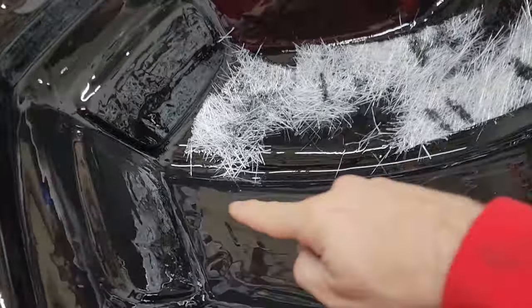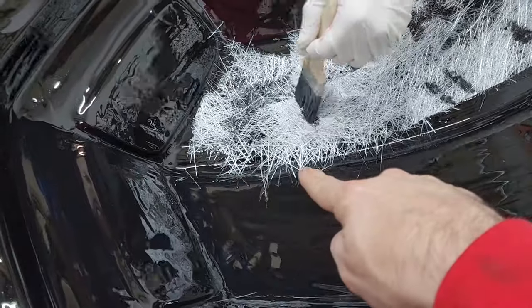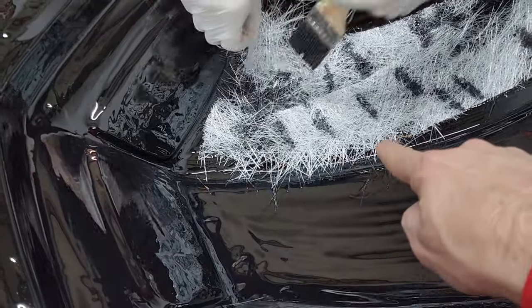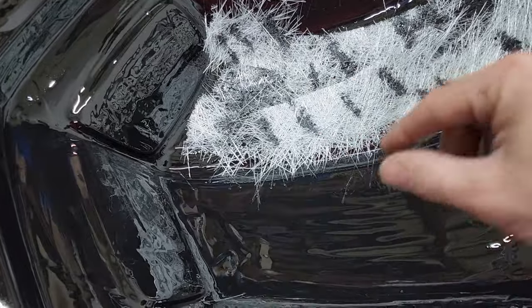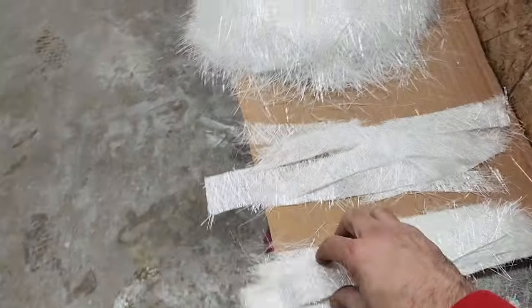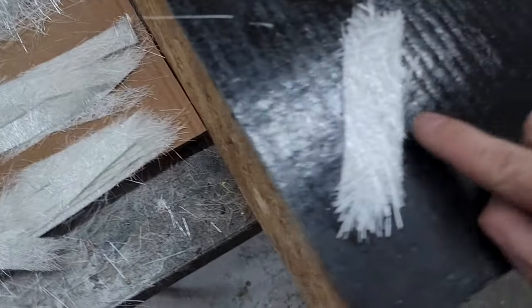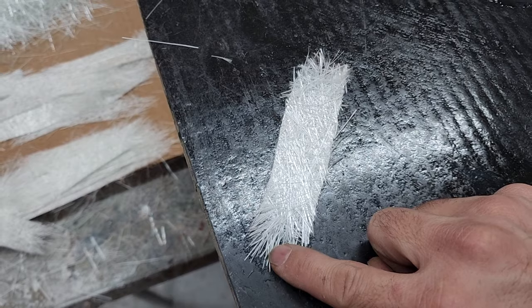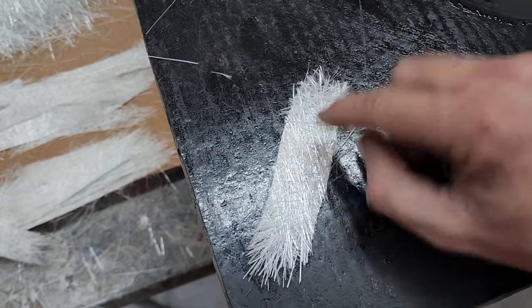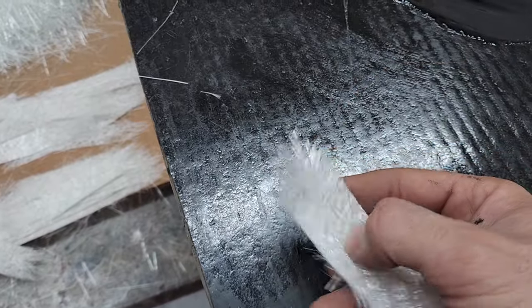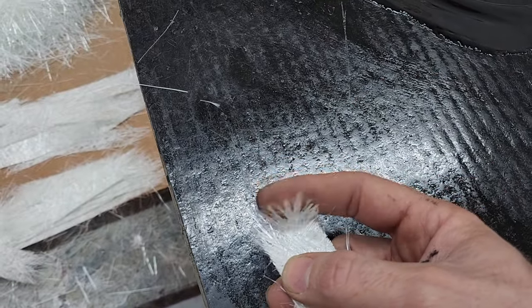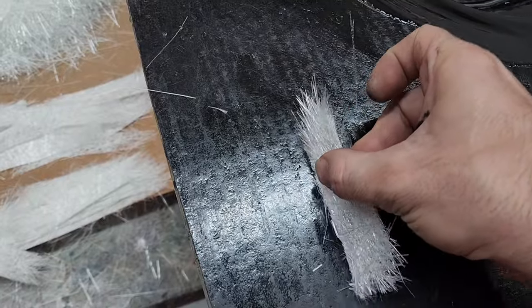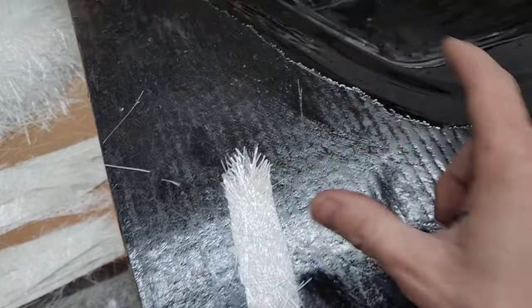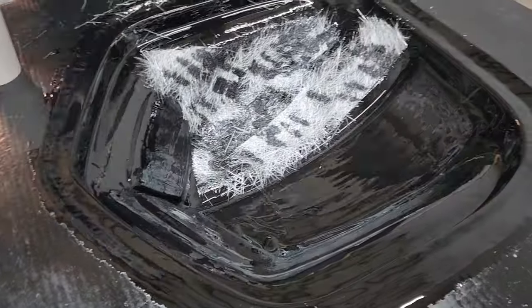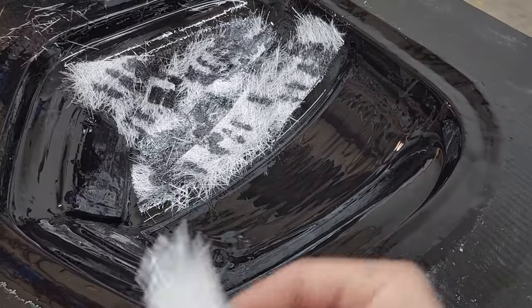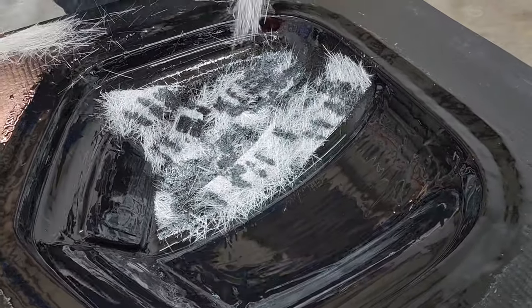Especially in real tight radiused areas like this, the grooves, you want a feathered, torn edge, not a sharp cut edge. Let me explain what I'm talking about here. If you were to imagine this piece, this part will blend much easier than this sharp edge here. So if you're trying to put this down into a curve, you'd really want to put the feathered end down into the curve instead of the sharp edge, which may not conform. So we pick the pieces strategically to go in specific spots so that they lay in there and they don't bridge. You don't end up with air pockets or any kind of a gap underneath.